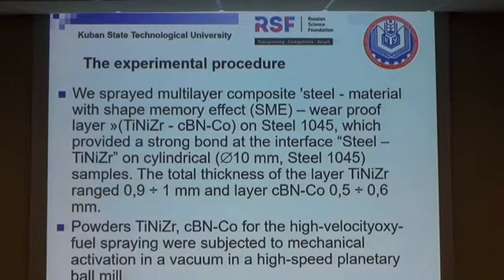The experimental procedure: we produced a multi-layer composition steel material with the shape memory effect. We applied a layer of titanium nickel zirconium with cubic boron nitride and cobalt on steel 1045, which provided a strong bond at the interface. Samples were cylindrical, 10 mm in diameter, of steel 1045 with titanium nickel zirconium. The thickness of the titanium nickel layer was near 1 mm, and the layer of cubic boron nitride with cobalt